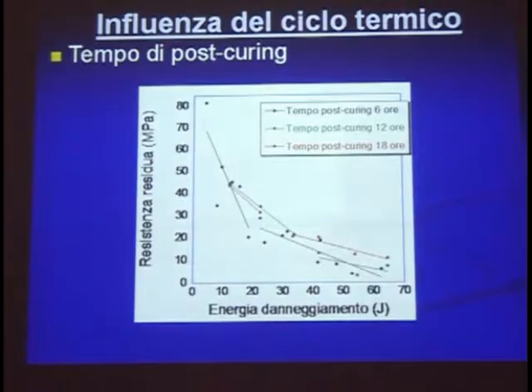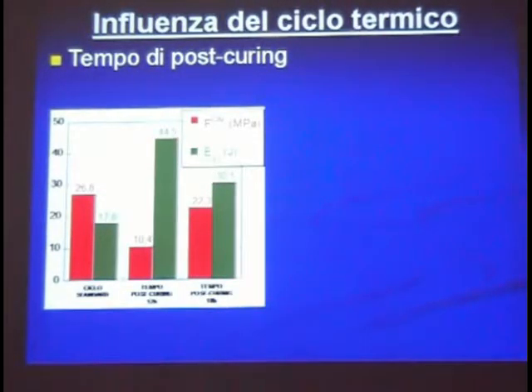These are the curves that we have been deriving for the post-curing time, 6 hours, 12 hours, 18 hours. You see there is a somewhat surprising upward behavior, which means probably that the standard 6-hour post-curing time is not optimal for this material. This is more clearly seen by comparing the parameters. The strength goes somewhat up and down. It is not very significant.